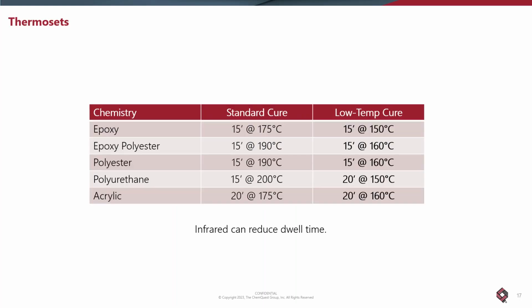Here's a little cheat sheet that shows standard cure of powder coatings: dwell times of anywhere from 5 to 20 minutes, but traditionally in that 15 to 20 minute range, and a cure temperature ranging from about 175 to 200 C. Simple adjustments to the binder system can get you down 20 or 30 degrees Celsius lower in temperature. And I'll give you some examples.